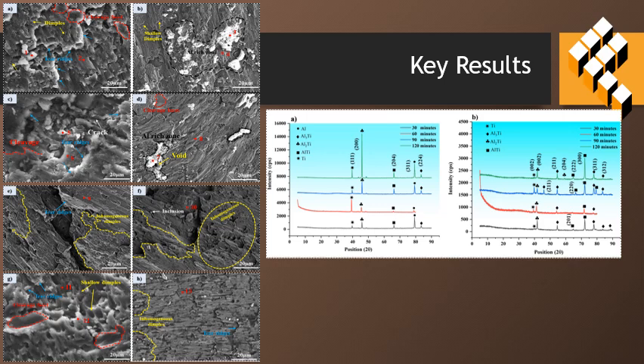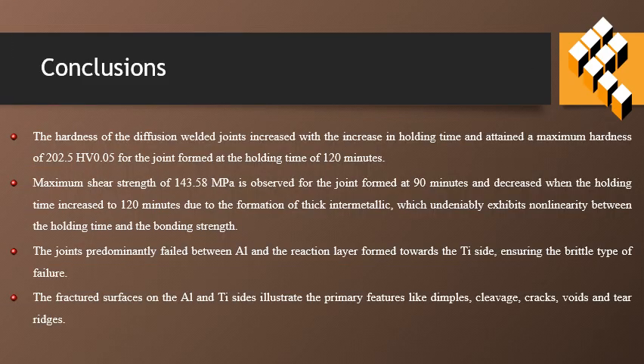These are the conclusions drawn from the current study. Maximum shear strength of 143.58 MPa is observed for the joint formed at 90 minutes, and it is decreased when the holding time increased to 120 minutes. The joints predominantly failed between the Al and the reaction layer formed towards the Ti side, ensuring the brittle type of failure. The fractured surfaces on the Al and Ti sides illustrate the primary features like dimples, cleavage, cracks, voids, and tear ridges.